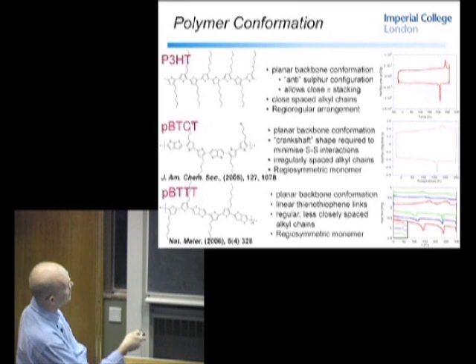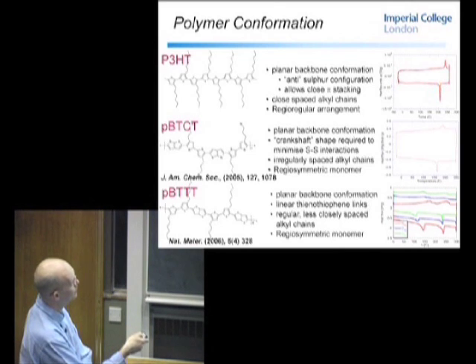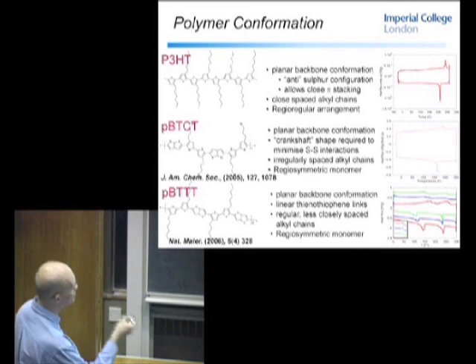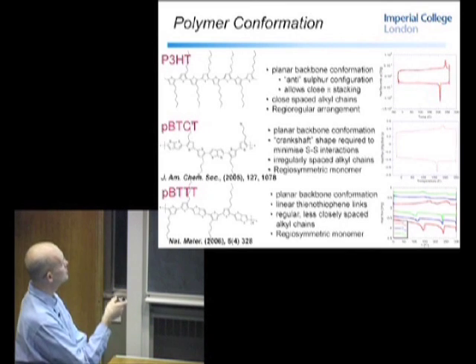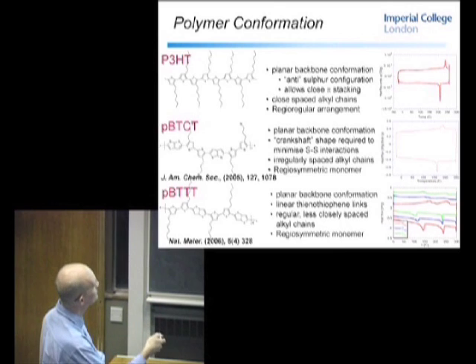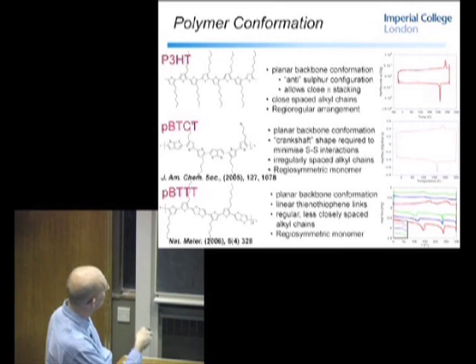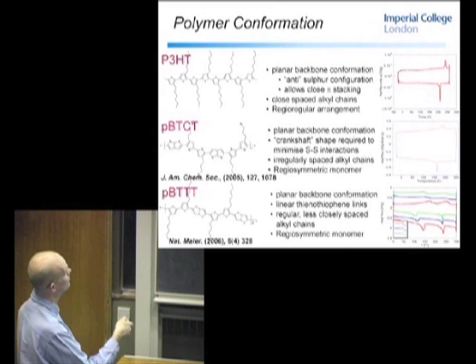And what I'm showing here is the thermal behaviour of the polymer. This is a DSC, so this is the heating endotherm, cooling back down, and the crystallization exotherm. And you can see here, this is a very sharp crystallization, and that's again indicative of a very crystalline material, pure material, narrow polydispersity, and high degree of regioregularity. And when you play around with this backbone shape, then you see that you can really depress the melt point and depress the crystallization point. There's other reasons why we put the 2,3-b unit in place, and I'll talk about that a little bit later.